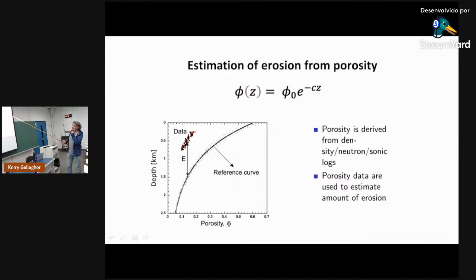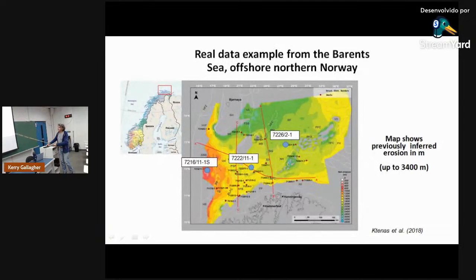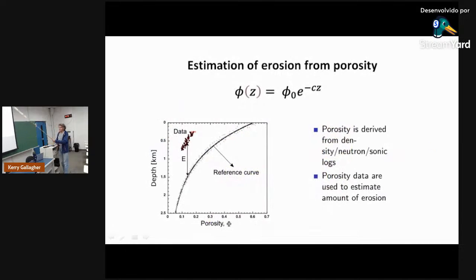And they might vary with lithology, and all that kind of stuff. So the idea of trying to estimate erosion from porosity said if we could define some reference curve in a place where there'd be no erosion, and we go over here where there's not much erosion, and then we go over here, and we measure porosity in our well, and maybe we have data that looks like this. So at this depth of 500 meters, from our reference curve, we expect porosity to be 40%. But what we actually measure is more like 10 to 15%. So the idea is that it's been buried more deeply, and then through erosion whatever this layer is has come up to the surface.